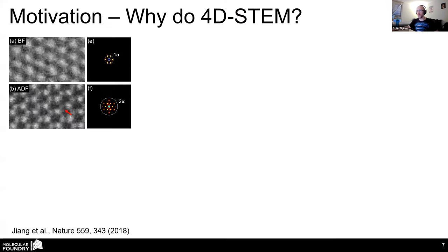So why would we want to do this? Here are two examples from the Cornell lab of a conventional imaging experiment on single layer thick molybdenum disulfide. And you can see the conventional incoherent bright field and annular dark field in A and B respectively. You can sort of make out the atomic lattice. You can vaguely tell which atom spots are the molybdenum and which ones are the two sulfur atoms. And on the right-hand side in the Fourier transform, you can see the resolution of the technique.